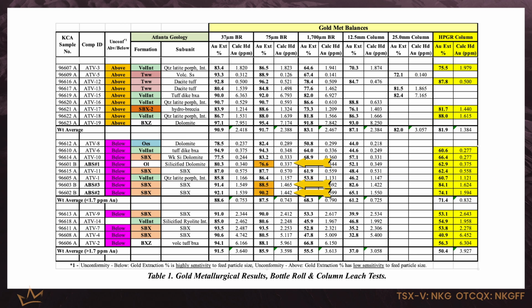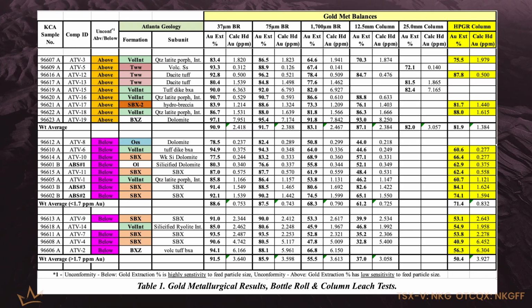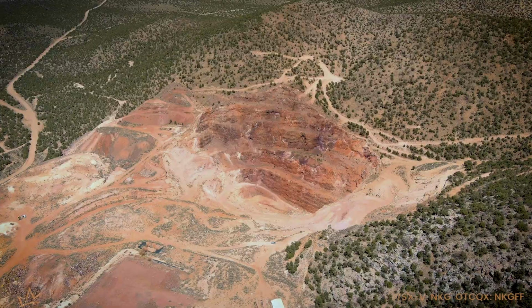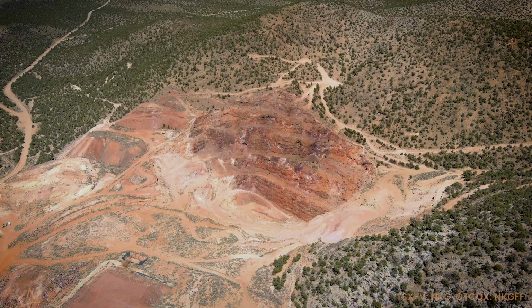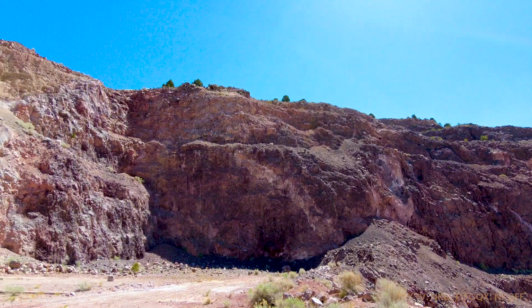We were getting mid-80s to low 90s for recovery at conventional milling sizes of 200 mesh. But crushing and leaching the silica breccia was not very successful, getting low recoveries. And by applying high pressure grinding roll to that silica breccia, we could improve the low grade recoveries by 10 or 20%, getting them into the 65-70% recovery range, which would make them suitable for HPGR crush in a conveyor stack heap leach. High pressure grinding roll, it's a perfect bullseye fit for highly silicified and abrasive rocks.